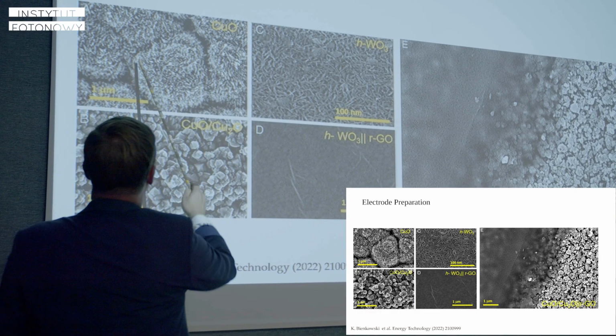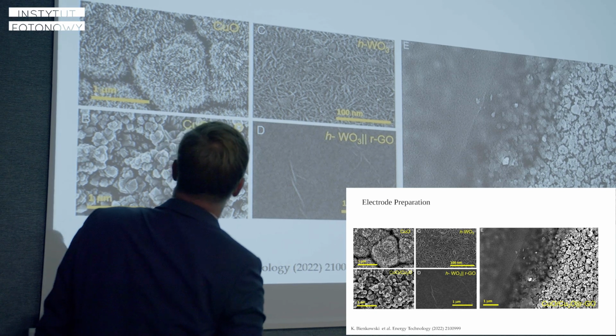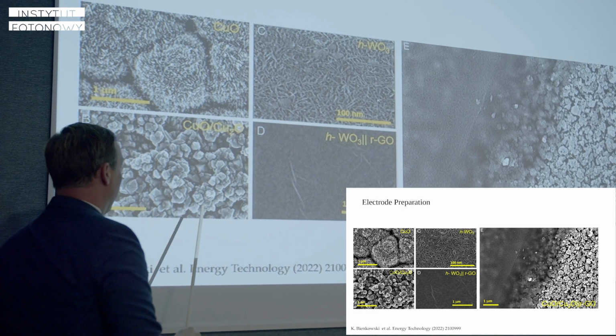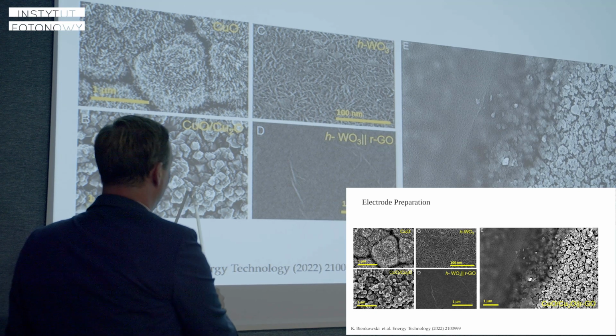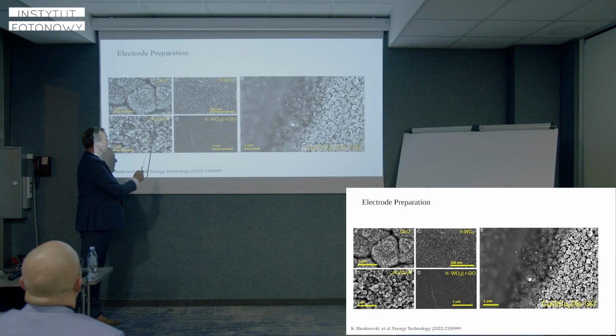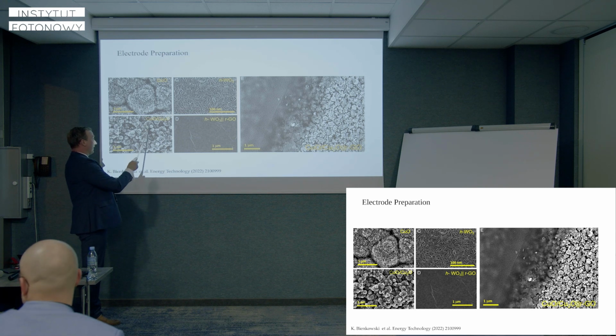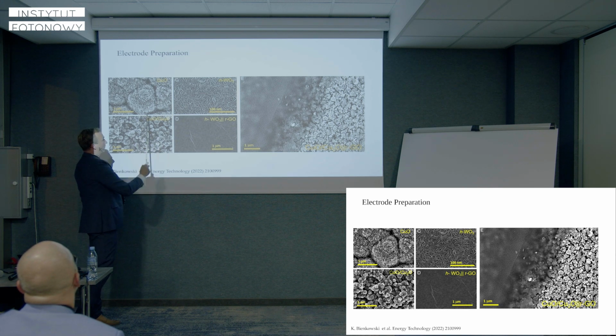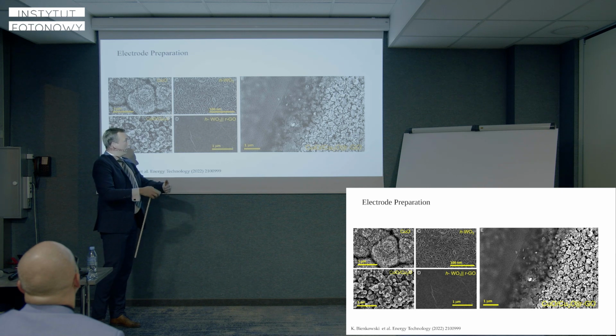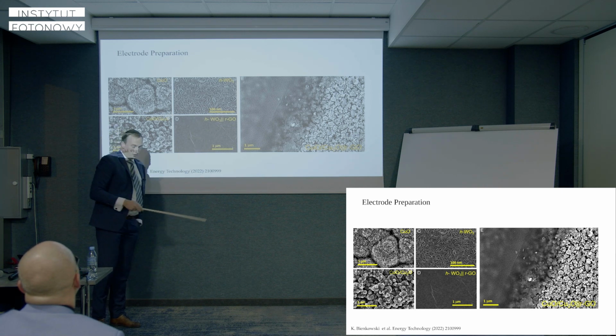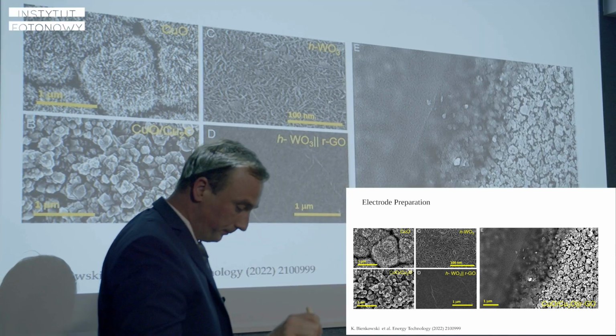It is nanoneedles here, but I don't see it very clearly. Nevertheless, we synthesize a copper-1, copper-2 oxide system. We deposit RGO on this mixed system, so copper-1 oxide and copper-2 oxide, and after this we put hexagonal tungsten trioxide. And after this, we put another layer of reduced graphene oxide.